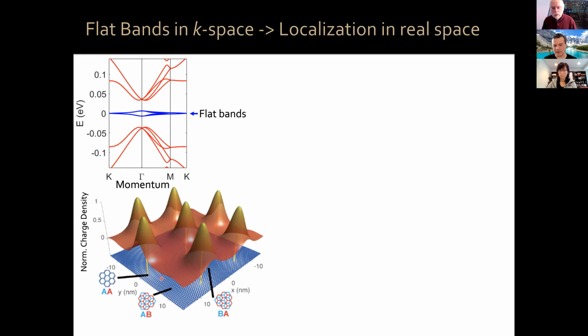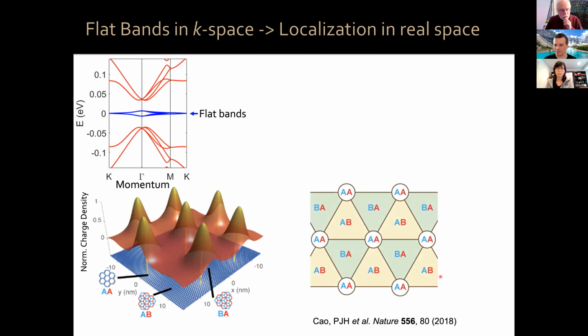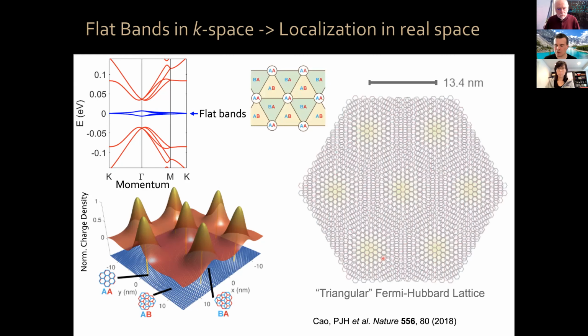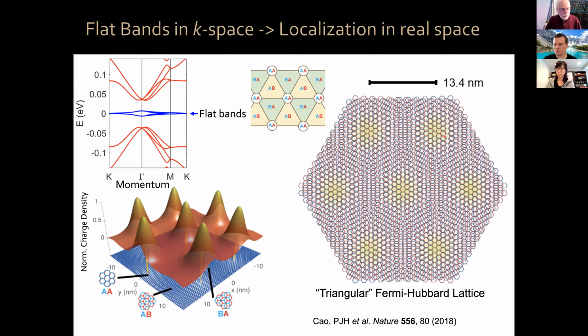These regions are tunnel-coupled by regions of AB and BA stacking, where due to the small twist angle, the registry of the atoms comes sort of out of sync, okay, and creates these AB-BA stacking regions. So schematically from the top, this is what magic angle graphene looks like. We have regions of AA stacking, where the electrons like to be, and those regions are tunnel coupled by regions of AB and BA stacking. In a slightly more realistic schematic, we have these AA regions, which here have these yellow circles, where the electrons like to be. These regions are 13 nanometers apart, okay?